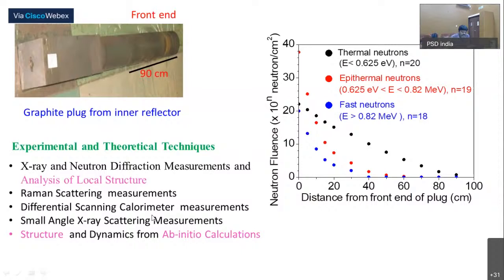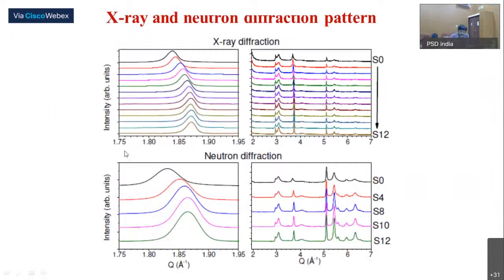We also did DSC measurement, small angle scattering measurement, and structural measurements, and we also did ab initio calculation to understand the release of Wigner energy. So these are the plots for the X-ray and neutron diffraction. We can see that this peak is shifting to lower Q with irradiation. S12 means the sample which has faced the maximum fluence. So this is shifting to lower Q, which indicates an increase in length.